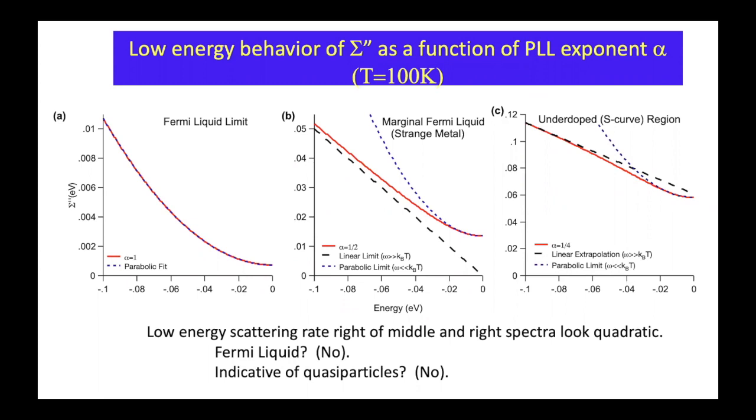Yeah, okay. So the question is about Kramers-Kronig, and what do you do because you need all frequencies? So there's two things you need. First, you need a cutoff at some deep energy, and we go quite deep. We go well past the bottom of the band, which is about half a volt. If we go to half a volt or a volt, there's very minor differences.